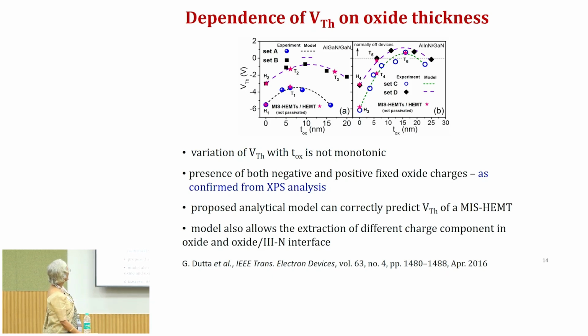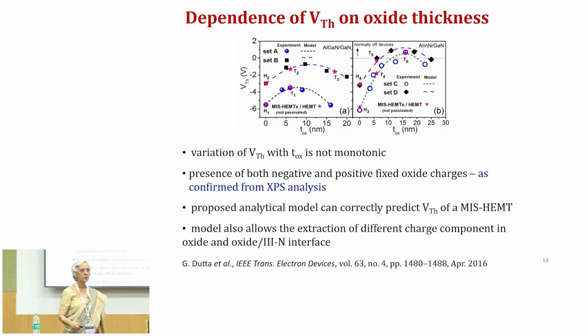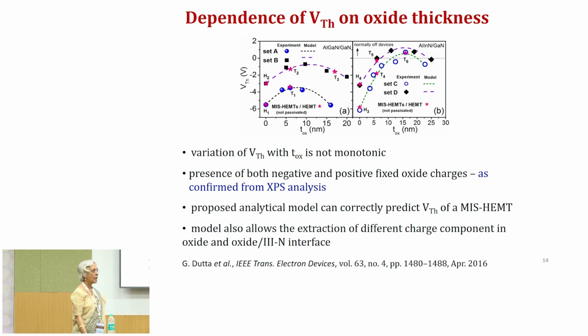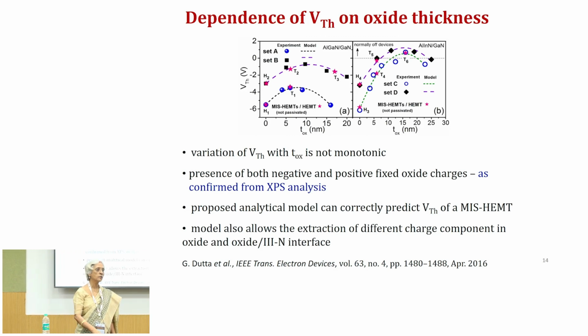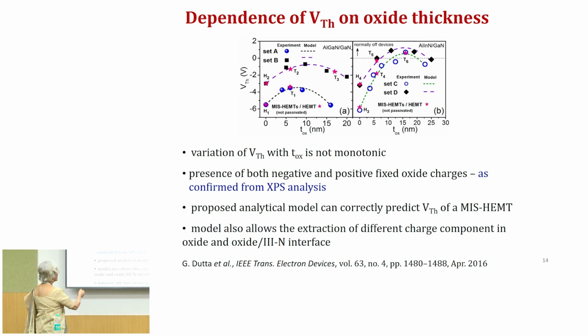So, we did a lot of experiments, and you can see these two comparisons between aluminum gallium nitride heterojunction and aluminum indium nitride gallium nitride heterojunction. We find that the variation of the threshold voltage with TOX is not monotonic. Now, why is it not monotonic? That is because the composition of the aluminum oxide that we deposited is not really uniform. While close to the interface we did have oxygen rich aluminum oxide, beyond a certain point it started to become more aluminum rich. As a result, we had presence of both negative and positive fixed oxide charge.